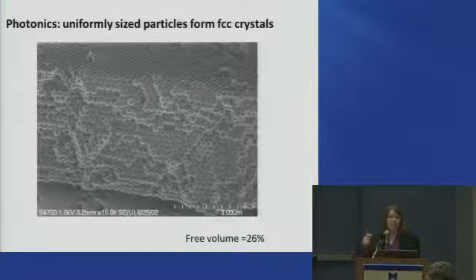And I looked at pictures of these and I thought, God, that's the most beautiful chromatographic material I've ever seen. And you can also potentially use it for electrophoresis because you have these pretty uniform pores. These are 200 nanometer particles, and so the pore diameter is on the order of what you have in polyacrylamide electrophoresis gels. And so we just have to figure out how to start making these. And so this was the first one. Well, we had made many, but we didn't have an SEM. So this was right after Delaware took delivery on a field emission SEM and proudly got this picture. And so I want to tell you about the work that we've done since then on these, getting better and better and better at making these things and finding very interesting properties of these things.